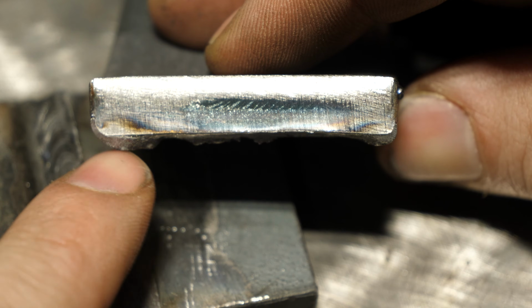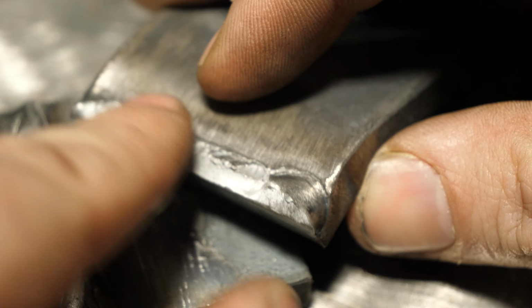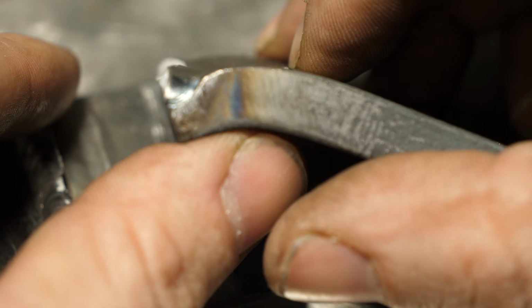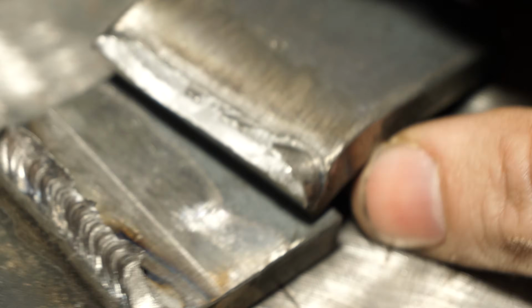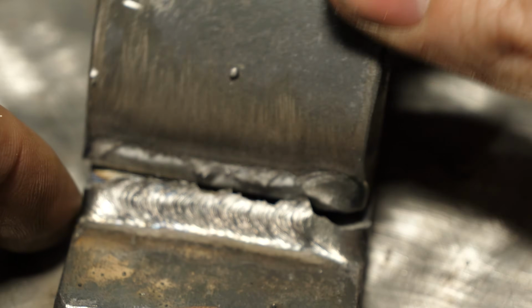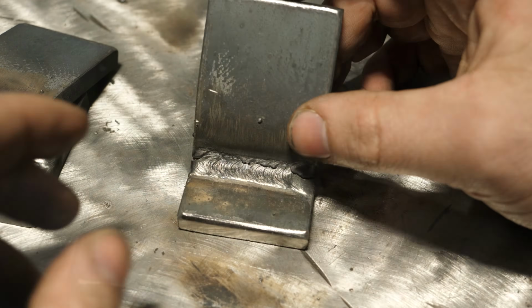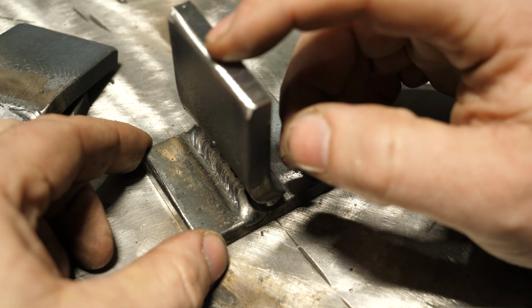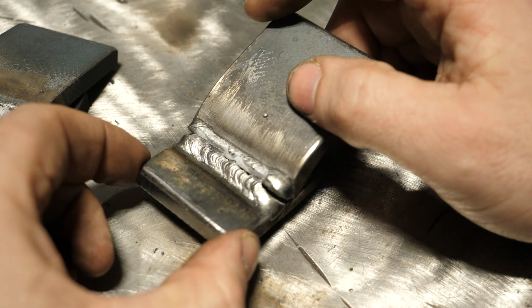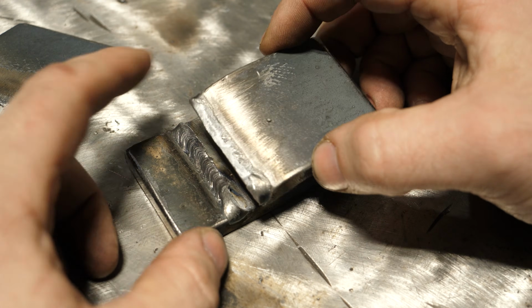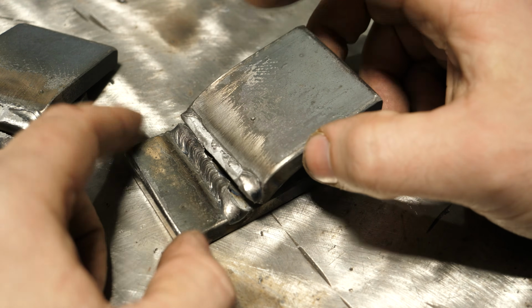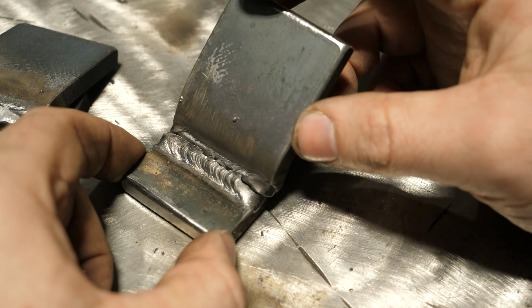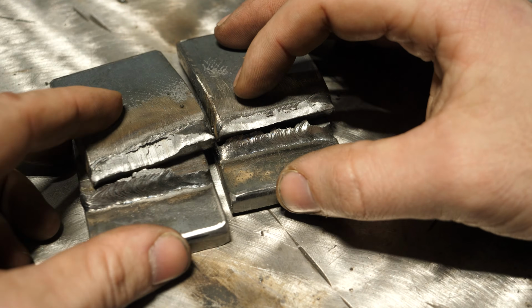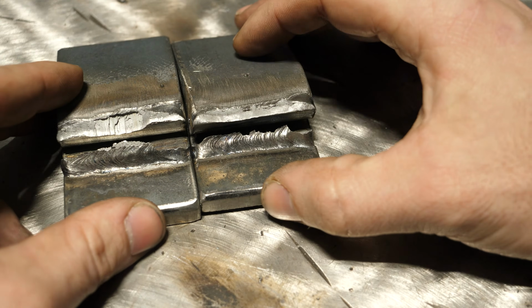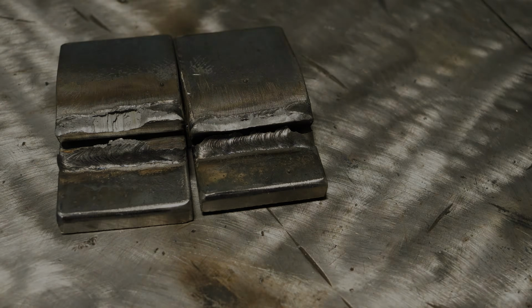The plate edge is virtually untouched, and it failed. It didn't peel off any of the plate, only the weld remains. So the weld itself was not as strong as the plate in this case. This is a common result when you bend it this way towards the face, but bending it away, I have not seen on any test where the weld itself broke. Pretty interesting there. Now let's compare and contrast the 7014 and 7018.